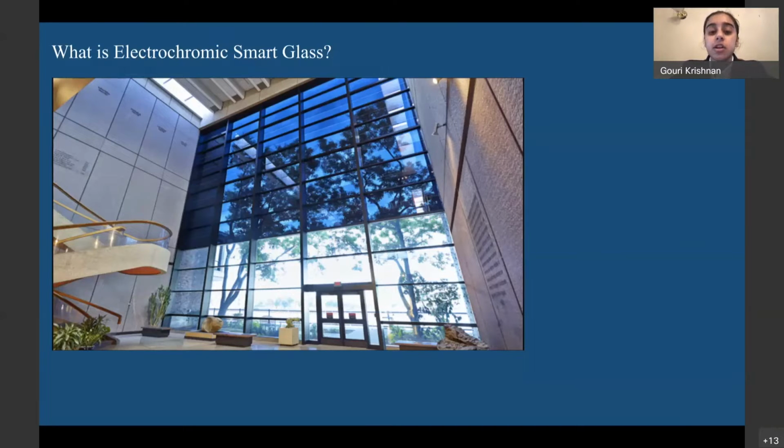This color change occurs due to a shift in the reflectance and transmittance spectrums of a material after an electrochemically induced reduction oxidation, or redox, reaction. With this project, we aim to improve existing electrochromic windows by designing a more efficient electrochromic coating that can undergo a reversible color change when exposed to smaller magnitudes of positive and negative applied potentials.